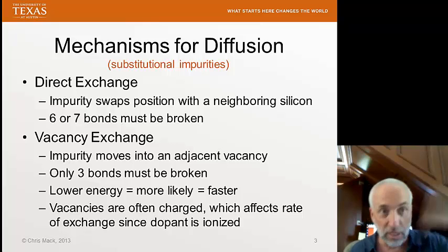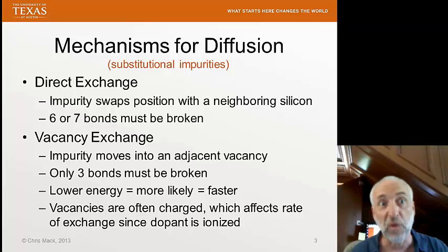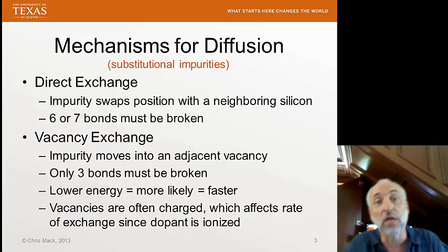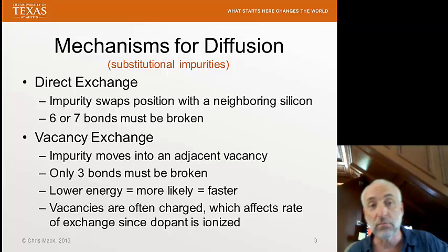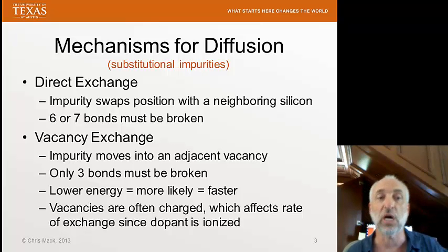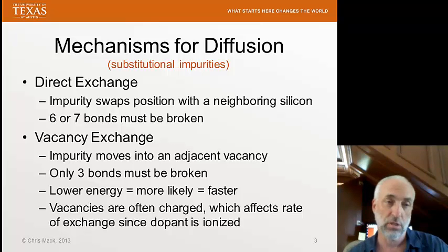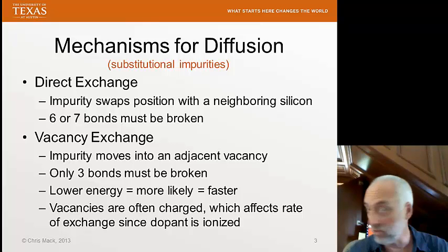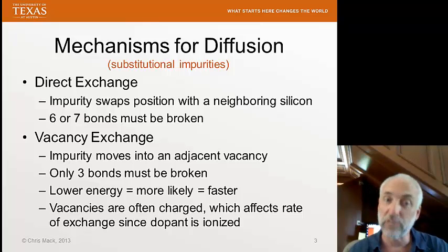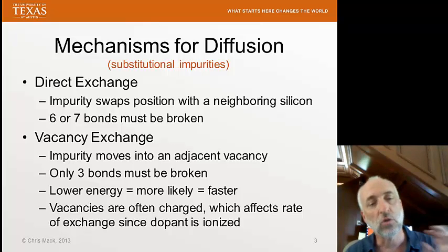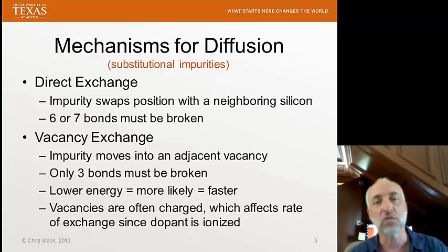Either the electrons move away and the vacancy becomes positively charged, or another electron falls into that spot to put 2 electrons where that bond would go, and that makes the vacancy negatively charged. Now there's 4 spots, so it's possible to even have charged -4 or charged +4, and anything between 1 and 4. So it's quite frequent that these vacancies are charged.